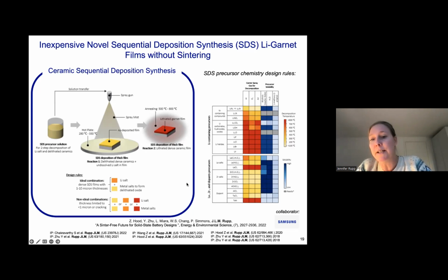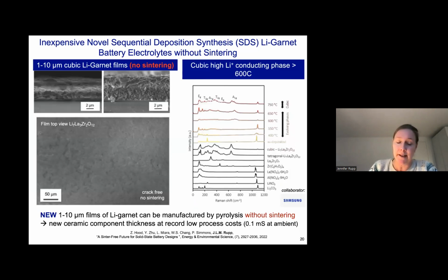In principle, we demonstrate the case in the published paper for a certain set of lithium and other cation salts that we transform into the lithium garnet oxide structure. But there are many options that you can adapt towards the synthesis chamber and environment you have, to play around and make a whole array of different new chemistries. Now, this is why this is cool from a ceramics perspective. You can see on the left side the nanostructures, and you can see that in the top view it's possible to make crack-free and dense films, and that's no fancy beauty. It's just the spray chamber.